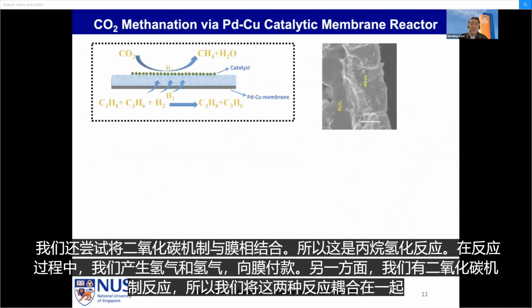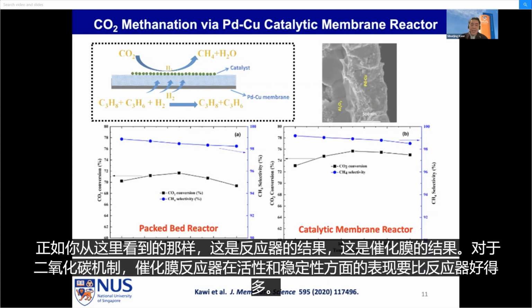We also tried to combine the CO2 methanation with the membrane. So this is the propane dehydrogenation reaction. During the reaction, you produce hydrogen, and hydrogen will permeate through the membrane. And on the other side, we have the CO2 methanation reaction. So we couple these two reactions together. And as you can see from here, this is the packed bed reactor result, and this is the catalytic membrane reactor result. For CO2 methanation, the catalytic membrane reactor performs much better than the packed bed reactor in terms of activity and in terms of stability.